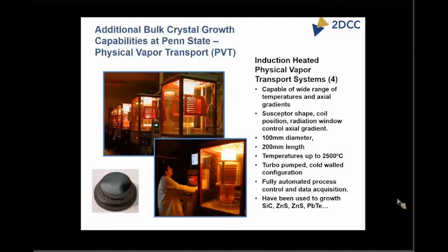These are large systems that can be configured up to 100 millimeter diameter, 200 millimeter length. And a key point is that it's capable of very high temperature growth, getting to 2,500 degrees C in these systems with the right design quite easily. And with turbo pumps, they're very clean, very high purity, fully automated. I said we've used these in the past to grow a variety of materials. So I just put this slide in here to make people aware that if there's a class of material where you think this type of process would be advantageous over CVT, for example, it would be available.